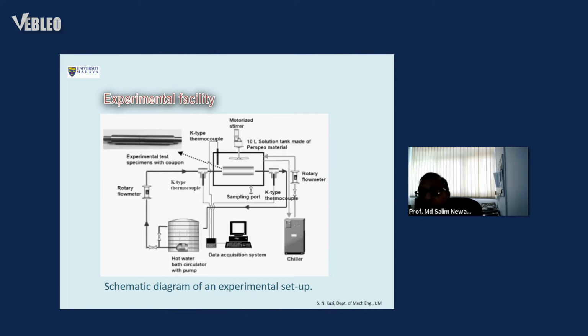In one of the setups, this is the test section, and hot water flows through it to raise the surface temperature to a high level, while the solution remains outside, submerging the test section. When the surface temperature goes up, the solubility of the dissolved salts reduces, and then it deposits on the surface.